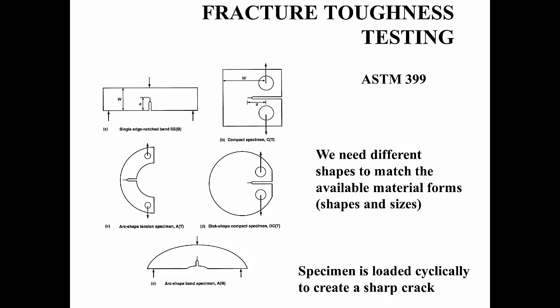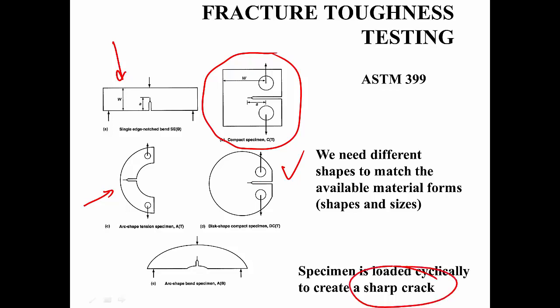For an actual test, I was saying that there are multiple geometries, and the reason that there are multiple geometries is that occasionally there is no possibility to actually form a test of the geometry of the compact specimen test. Sometimes the only thing that you are going to have is something of this form, or if you have a tube, then it's difficult to machine a square specimen there, and this shape is used. If you have a bar that has a round geometry, you can use this one, and on it goes. There are lots of geometries depending on what is the product that you are interested in testing. And for all of them, there is a machined notch, and then there is a sharp crack at the tip of that notch that is formed by fatigue testing, by fatiguing the specimen.